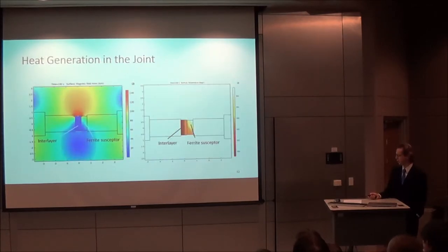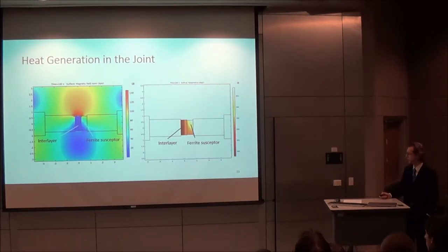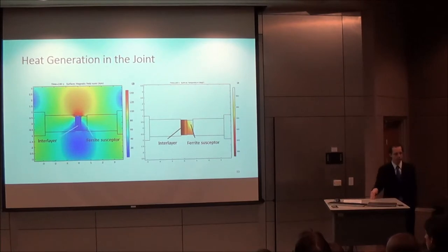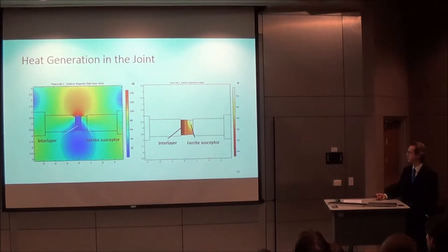And so looking more closely, we can see the interlayer, the ceramic and the metal base materials, and the ferrite susceptor. And then this is from the heat generation computation, where at the end of 3 minutes of heating, the interlayer has reached easily high enough temperature in order to melt the interlayer. So these results were taken to mean that this approach can be used in an experiment. We can actually join a ceramic and metal using this method.